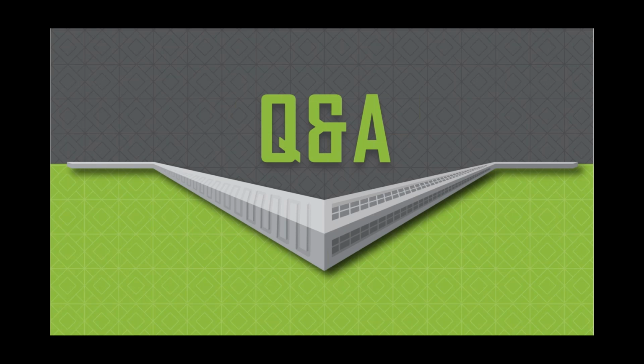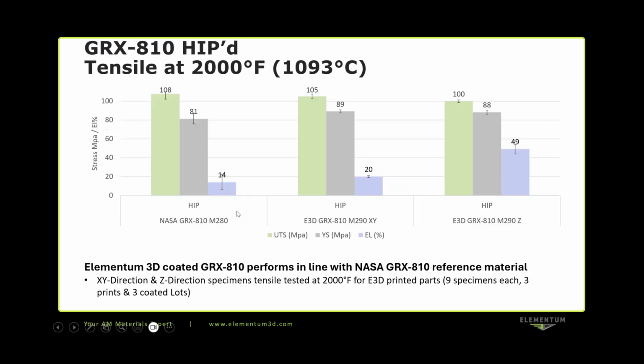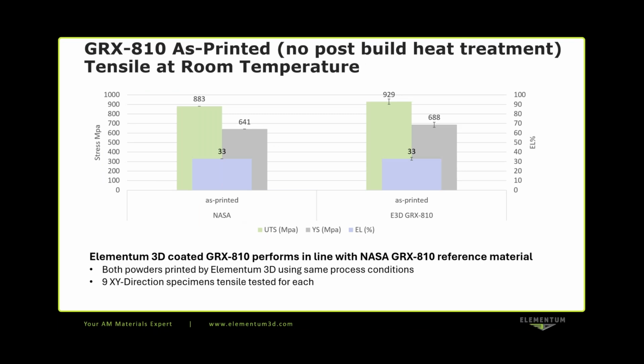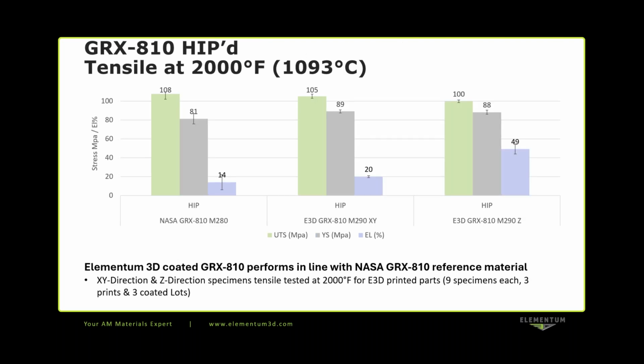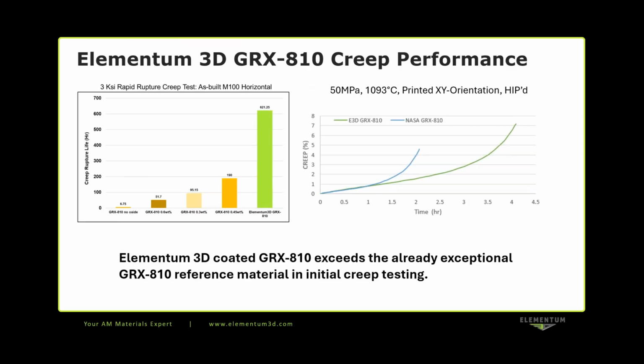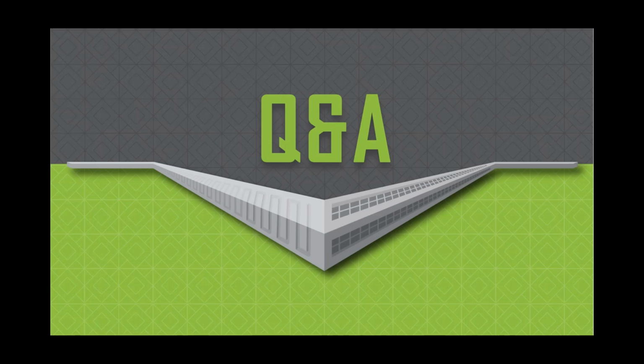So the first question is, are there results from the as printed condition or printed plus HIP? So the results I shared, if the question's addressed to me, these ones here were as printed with no HIP at room temperature. And then all of the other results are with HIP at temperature. So this is with HIP. And these creep results are also with HIP. And I will add that we do have a paper out there which provides some of the initial results on the EOS M280, and we have some additional papers that will be providing that include both the as-built or non-heat treated condition and the HIP condition, and we can send those papers or links out to folks as needed.